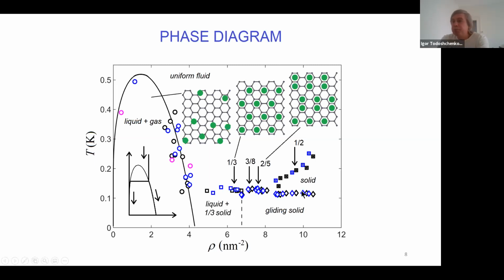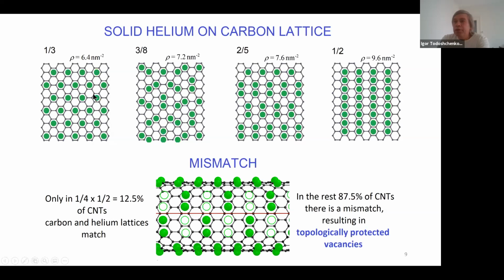with vacancies. Here I again illustrate this 1/3 phase and the 2/5 phase suggested by Greywall. In addition to this dimer phase, we also suggest a more symmetric dimer phase at the coverage 3/8. And at even higher coverage, this is basically the maximum coverage for monolayer helium on graphite or on the nanotube.